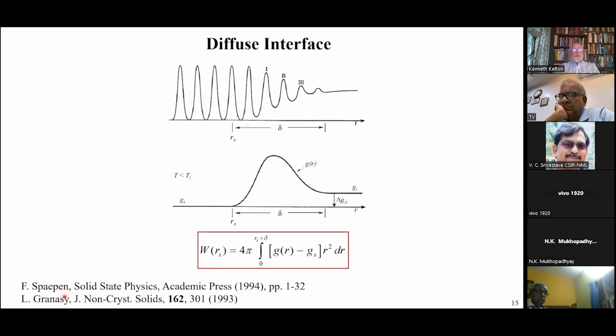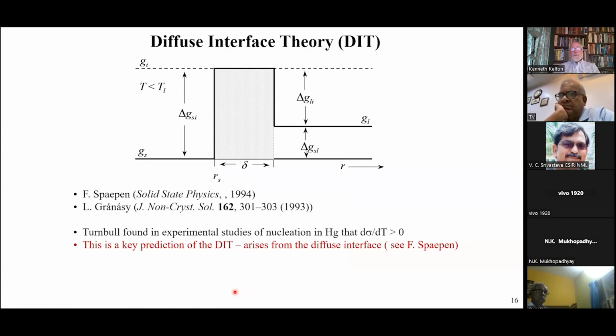Independently, Franz Spaepen and Laszlo Granasy, back in the early 90s, came up with a solution. What they said was, well, we don't know what the profile looks like, but let's at least assume that we have a diffuse interface, and they approximated the free energy by a step function. Now, I don't want to go through all the mathematics here, but you can find it in Spaepen's or in Granasy's papers. One key point that comes out of this diffuse interface theory is an explanation of something that David Turnbull found when he first started looking at nucleation of mercury in mercury. What he found was that to fit the nucleation data that he was experimentally measuring, he had to assume that the temperature dependence of the interfacial free energy was greater than 0.